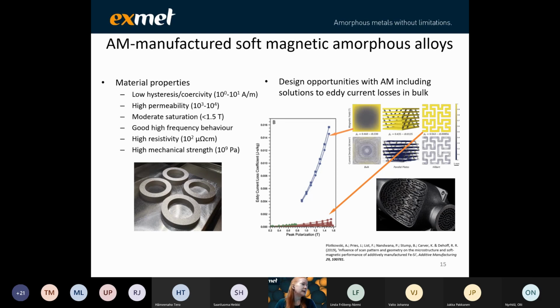This graph, which has eddy current loss on the vertical axis, tries to show that the bulk, the first picture of a design of the 6 designs to the right, points at the blue curves in the eddy current loss. That's what happens if you measure on the bulk. But by using these various geometries to break up this bulk and still build using structures that are very useful and buildable by AM, you can, by design alone, lower the eddy current loss to what the second arrow points at the bottom of the graph.